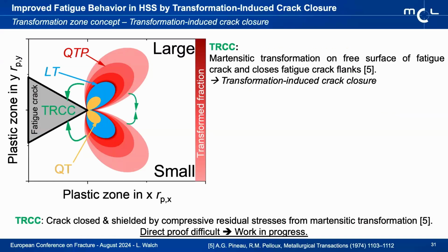If you look then at the general mechanisms that are known for transformation-induced crack closure to see if that's actually what's happening, of course, the one that's most simple is just transformation-induced crack closure based on the compressive residual stresses that are introduced by martensitic transformation and the associated increase in volume, which leads to crack tip shielding.